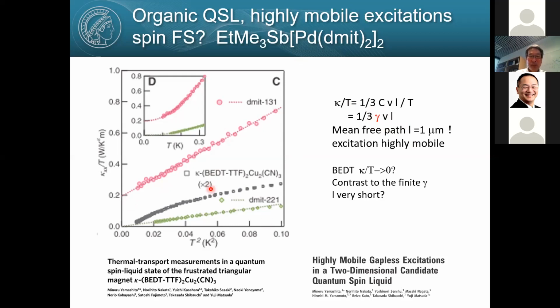On the other hand, for the other compound, the BDT compound, they find kappa over T goes to 0. That means the mean free path for the BDT compound is much shorter, or localized. But in this case, DMIT, you seem to have mobile fermions forming a Fermi surface, giving rise to finite gamma. And we roughly know the velocity of spinons and gamma from specific heat. From this, you can estimate the mean free path of the mobile carriers, likely spinons. And the estimated mean free path is as long as 1 micrometer, huge. So you have something like a clean metal.